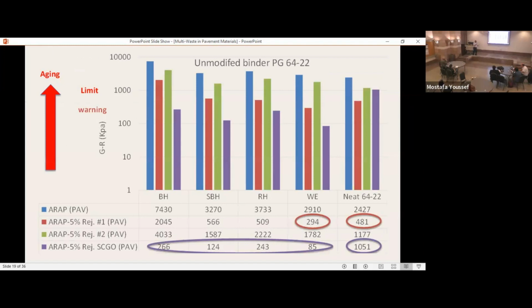Now, with respect to the Glover-Rowe parameter, we evaluate the binder alone with just the RAP, and that binder is aged in the lab to simulate field aging. And we do the same with the rejuvenators and the ash for all three rejuvenators. So by looking at this column here, this is our binder aged, the first row. The second row will be aged with Rejuvenator 1, Rejuvenator 2, and Rejuvenator 3. The higher the value, the higher the susceptibility to fatigue cracking.